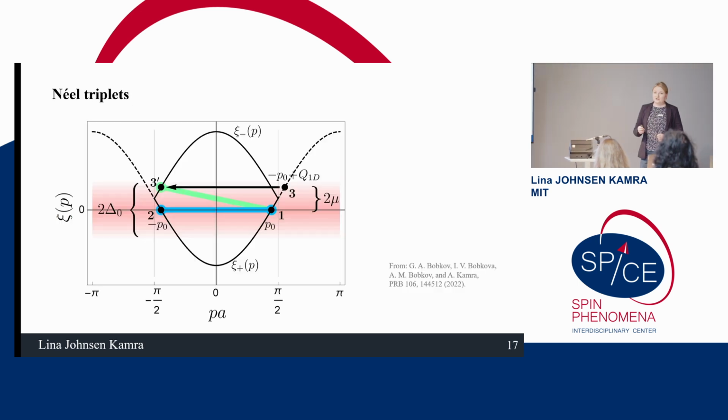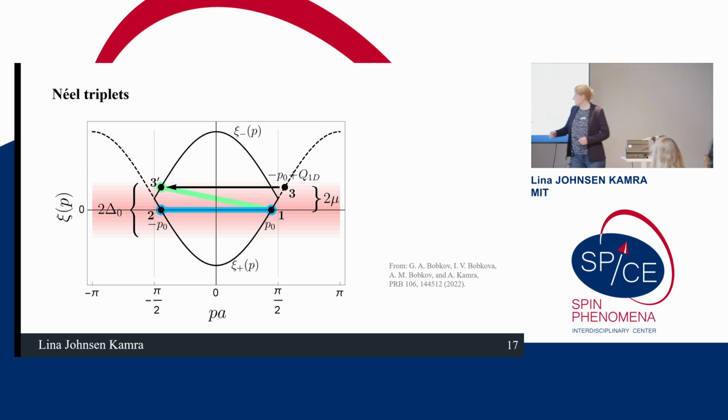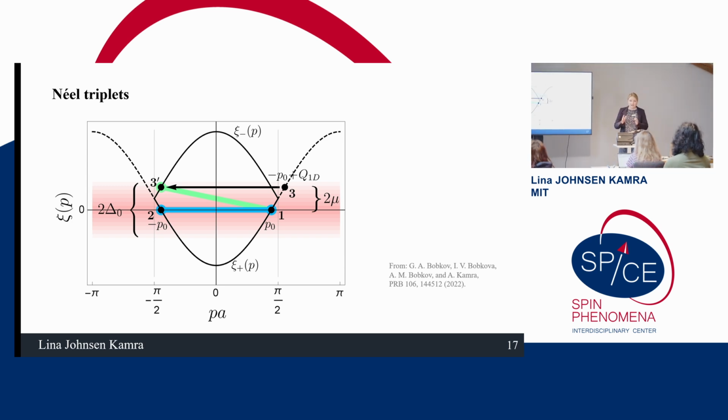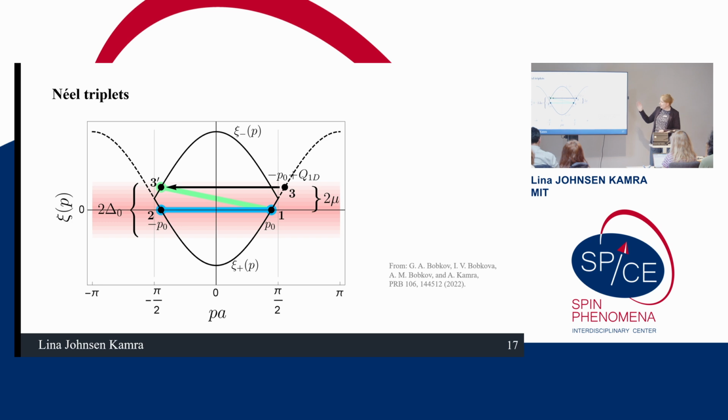Now, I cannot talk about this topic without pointing out this very good paper where they studied an antiferromagnet-superconductor structure. Here in particular, you just see a normal metal band, which, if we consider an antiferromagnet, we now don't just have the lattice constant as our periodicity, we have two sublattices, which means that we double the length of our periodicity, which means that we have to make the Brillouin zone half. And in this case, we have to fold the bands inside.